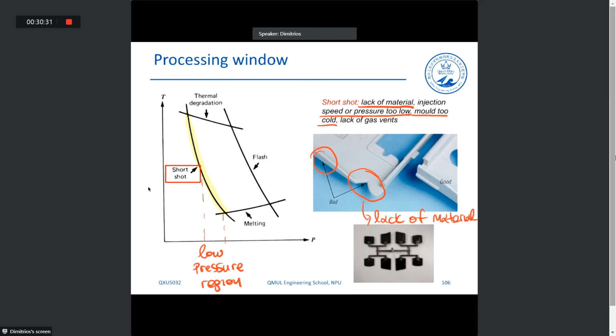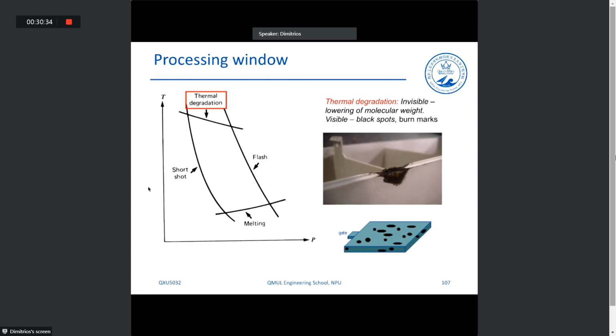Now, thermal degradation is also very important. If we use processing temperatures that are higher than the degradation temperature, then our polymer can degrade, okay? So if we are within this range here, we are already at very high temperatures, and because of very high temperatures, we can have significant problems in terms of performance. When it is visible, it can look like that, when we have black spots or burn marks. Okay, this is how it can look.